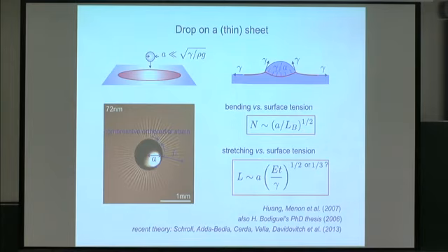And what they find out is that if you count the number of wrinkles around the droplet, this number is related to the bending length scale by this relation. So by measuring the number of wrinkles, you can deduce the bending length scale. And one issue which was a bit more tricky, and I'm not certain, maybe Dominique Vella can confirm what is the best relation.